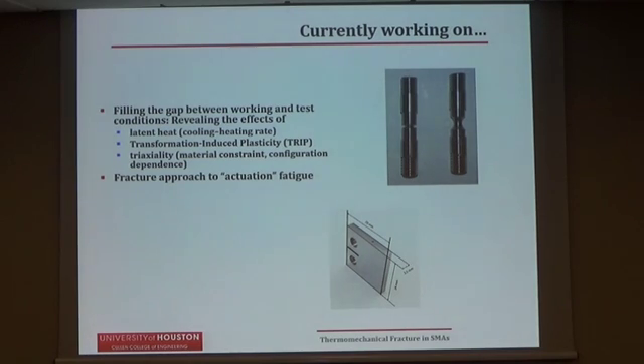I'll finish with one comment here. So if we want to compare, let's say, actuation fatigue, so fatigue at a constant load and thermal sweeps, thermal cycles, to mechanical loading, it will be the case of a delta K, the difference in the stress intensity factor, of around 10, although the load remains constant. So we are talking about a maximum load that is 10 times higher than the minimum load in the superelastic case, in the mechanical loading case.